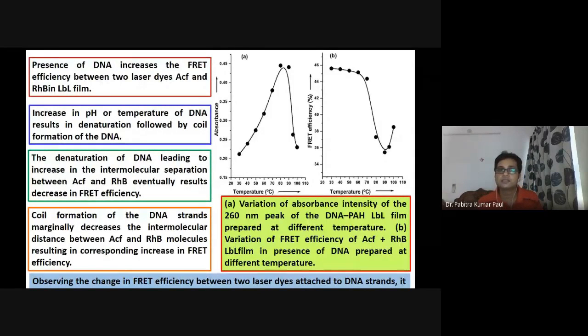So here you see this curve, the temperature versus FRET efficiency. After denaturation, the FRET efficiency increases. So at this portion, if we monitor this observation in some situation, we can have information about the structure of the DNA. So coil conformation of the DNA strands marginally decreases the intermolecular distances between the acriflavine and rhodamine molecules, resulting in a corresponding increase in FRET efficiency. So this is another example of how FRET is beautifully used to understand the conformation of the DNA. Observing the change in FRET efficiency between two laser dyes attached to the DNA strands, it would be possible to detect the altered DNA conformation in the changed environment.